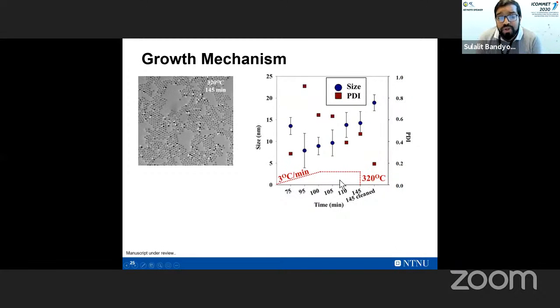So what I want to show here is that the size of the particles slowly increases, whereas the polydispersity index gradually decreases. And this is an indication that there are secondary growth processes happening, in which the small particles are most likely dissolving back into the solution and reprecipitating on the bigger particles, a phenomenon which is called Ostwald ripening, due to the solubility of the particles.